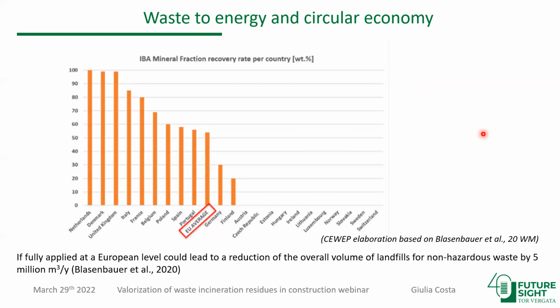Now, looking at the recovery rate per country, we see large differences. Overall in Europe, slightly more than 50% of the bottom ash mineral fraction is recovered, mostly in countries such as Netherlands, Denmark, and UK, but also in Italy and France. It is more and more recovered. In other countries, instead, due to the concern on the potential environmental problems of using these materials, it is not.